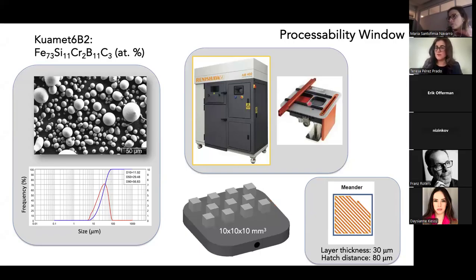So this is only a few centimeters, like 5 by 7 centimeters, the size of the build platform. And to start, we make just cubes, simple geometry specimens, and the side of these cubes is about 10 millimeters. Like I said before, we use a simple scanning strategy, meander, and we also fix the layer thickness and the hatch distance, so the distance between two laser passes.